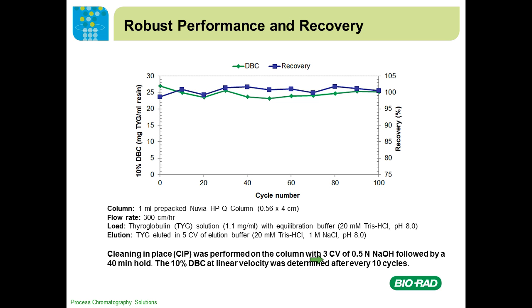For the cycling study, between the binding studies, we used 0.5 molar sodium hydroxide for sanitization and held it for 40 minutes. Over the 100-cycle study, we can see the binding capacities remain unchanged or change only slightly, and the recovery is still unchanged. That indicates the resin is very stable, and you are able to use 0.5 molar sodium hydroxide for sanitization.